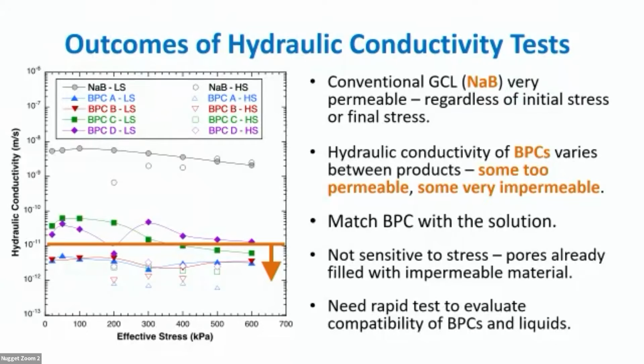And that was true whether we started with a low stress test shown here. These are the solid, and then the high stress tests with the open circles. They were all very permeable, a little less permeable with high stress, but still far too permeable than we would prefer. We'd like to have our hydraulic conductivities be below this orange line here at 10 to the minus 11 meters per second. So you can see we're nearly 1,000-fold too permeable with the conventional GCL.